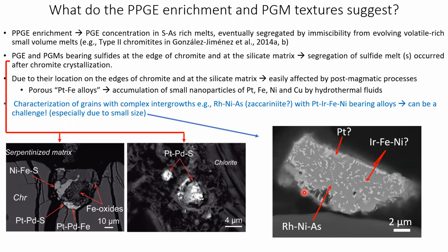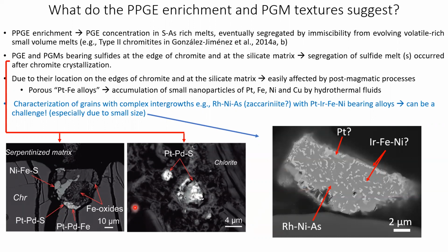Well, the PGE enrichment resembles that from the type 2 chromitite described in Jose Maria's works. And the interpretation of this is that sulfide melts collected incompatible PGE, and these sulfide melts were segregated by immiscibility from small volume melts. The observation that the PGE and PGM, bearing sulfides, are located at the edge of chromite and in the silicate matrix supports this hypothesis, and suggests that the segregation of the sulfide melt probably took place after chromite crystallization. And then, due to their location, this primary PGM were easily affected by post-magmatic processes.